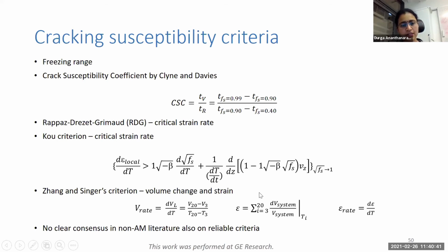Then we also have this Zhang and Singer's criterion, which was specifically for nickel-based superalloys, where they tested a lot and found that the shrinkage, the volume change that happens during solidification, and the strain associated with it, can maybe be predictors of crack susceptibility. But the point remains that there is no clear consensus, even in the non-AM literature, on what are the reliable criteria we can use for predicting crack susceptibility.